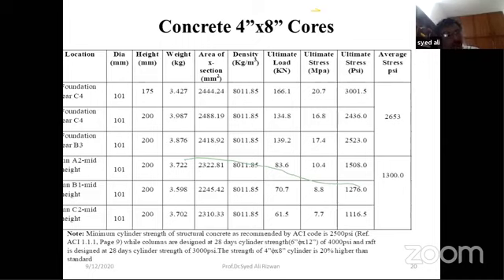Please remember that 4 by 8 cores give higher strength than 6 by 12 cores. Although they are allowed by ACI and ASTM, for 4 by 8 inches cores, you have to test at least 3 cores or 3 cylinders at one time. And for 6 by 12, you have to test at least 2 at one age.